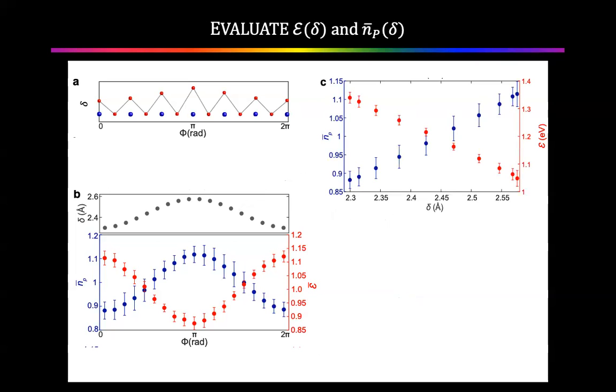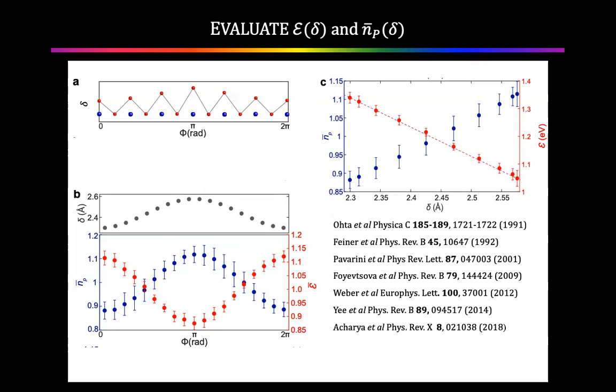So when we do that, we can plot charge transfer energy as a function of apical distance. Look at that line there. Consistent with decades of theory, the slope of that line is near 1 electron volt per angstrom, the way it should be from a hand waving argument. So what we're observing is that when you move the apical oxygen atom back, it diminishes the splitting between the 2p6 state and the empty d state. That's an empirical fact in the density of space.